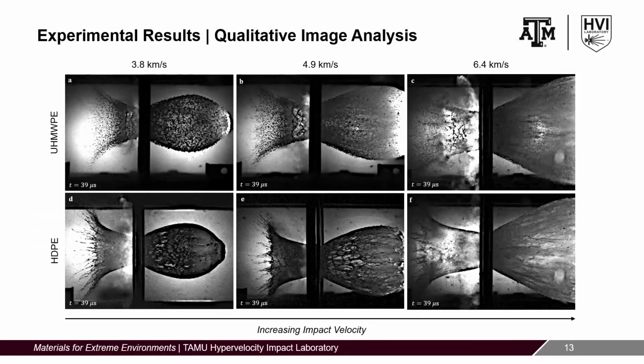A single frame is taken from each of the previous videos at 39 microseconds for comparison. The series of images indicate that the debris clouds of ultra-high molecular weight polyethylene tend to be composed of fragments, and the average size of these fragments in both the front face and back face debris clouds decreases with increasing impact velocity.